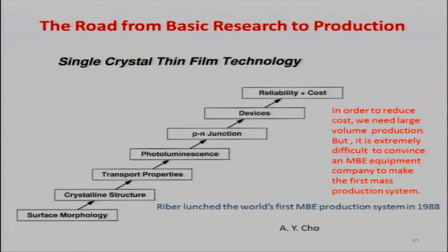And of course, the next level higher is looking at the photoluminescence. Now you look at the minority carrier device. It's harder yet. And then you can make PN junctions. Good PN junctions do not come easy; you have to have a very smooth interface and abrupt doping profile changes. After you have done all that, I can start making devices. So you make a device, you can publish a paper. But the important thing is, you can't just make a device which lasts 10 minutes, get data and publish a paper. You have to make a device which will last 10 years and 20 years to be any useful.